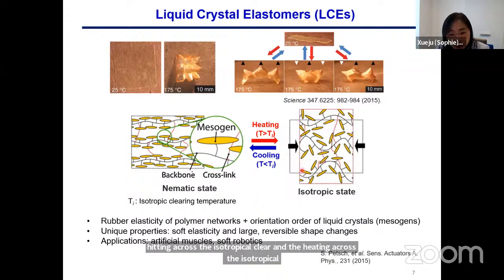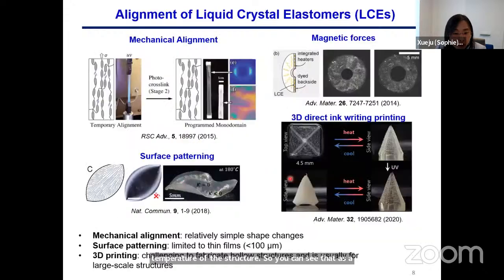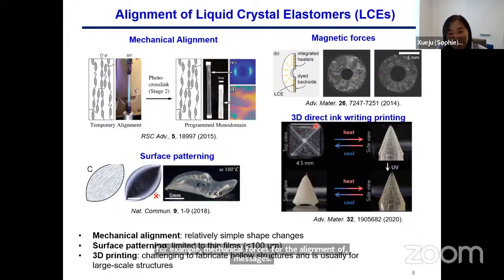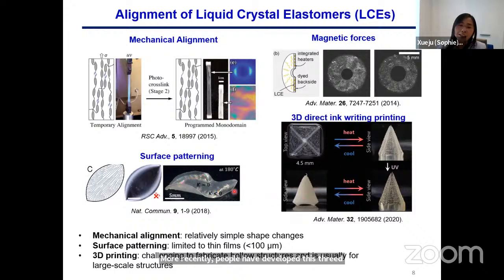So you can see that the reversible shape changing behavior is closely related to the mesogen alignment, right? Current alignment techniques include mechanical alignment, like stretching and bending for relatively simple shape changes, and also surface patterning that can enable very complicated patterns, but is usually limited to thin films below 100 micrometers thick. People also use external fields, for example, magnetic fields for the alignment of mesogens. More recently, people have developed 3D direct ink writing, or 3D printing, to create 3D LCE structures where mesogens are aligned along the printing path due to extrusion-induced shear stress.